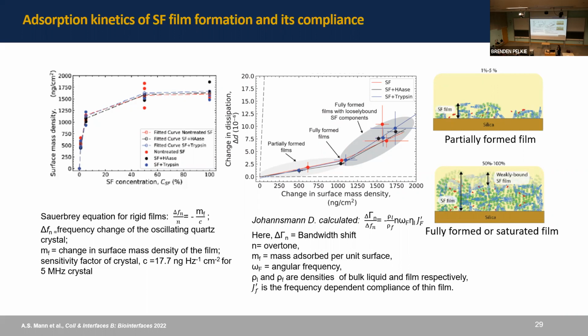And the inverse of this is the shear modulus of the thin film. And we identified two different regions where for the partially formed films, it is less rigid. And as we form a fully formed film with an outer layer of loosely bound molecules, then the compliance increases, so it becomes more elastic.